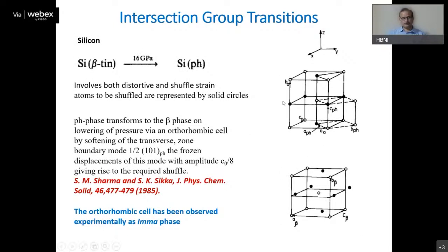So let us take another famous example of an intersection group transition. We know silicon actually transforms to many phases. It has a rich phase diagram under pressure. The initial phase of silicon is a diamond phase, and at about 12 GPa it goes to the beta-tin phase, which is a tetragonal phase. As you further increase pressure, it transforms to the primitive hexagonal phase. But again, this transition is also through some intermediate structure, which describes the symmetry of both these structures.